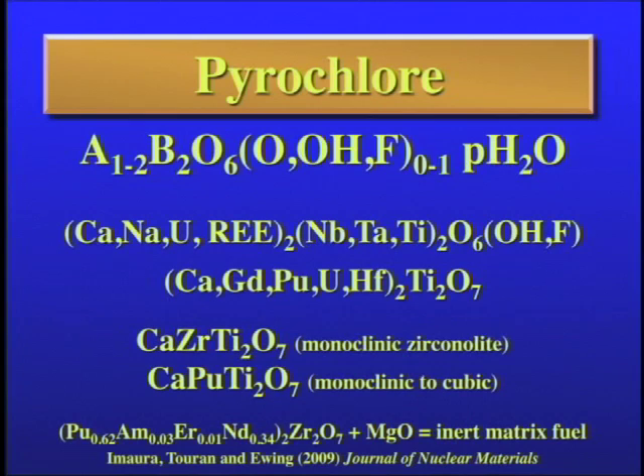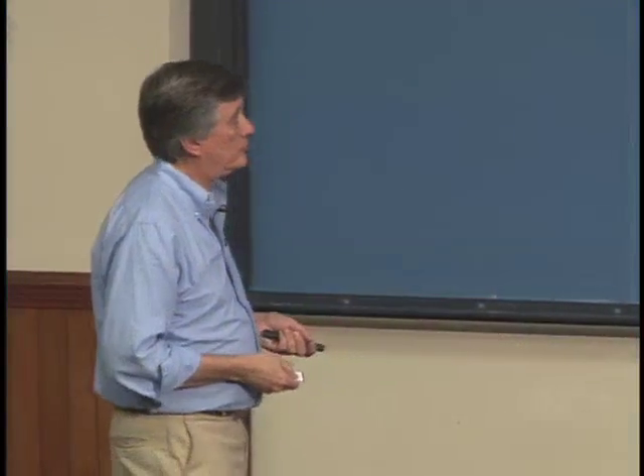Also, just in passing, I'll say the pyrochlores become important as an inert matrix fuel, mixed with other things so that you get the right thermal conductivity. And it's important because this is a structure that's very flexible. There are over 500 synthetic compositions with lots of fascinating chemical, electrical, and magnetic properties. And because the structure is so flexible, you can tailor the composition. You can burn some plutonium, but for a fuel, you have to add some rare earths. You have to increase the reactivity of the fuel, and that depends on the composition. And so you need a structure that gives you the flexibility to do that.